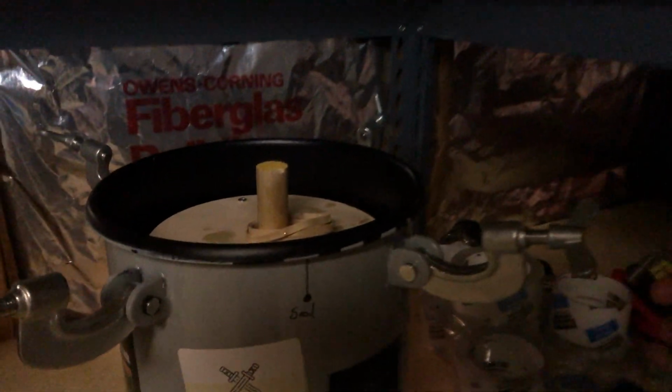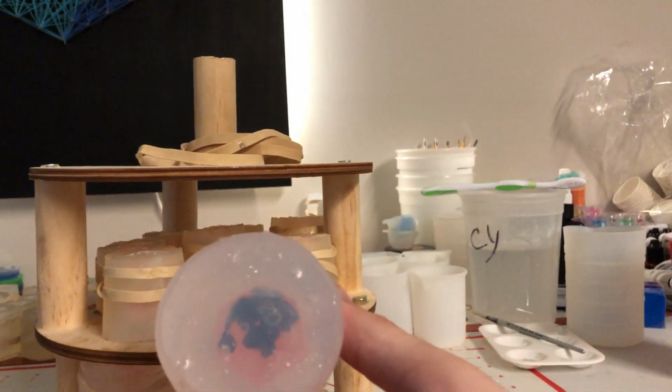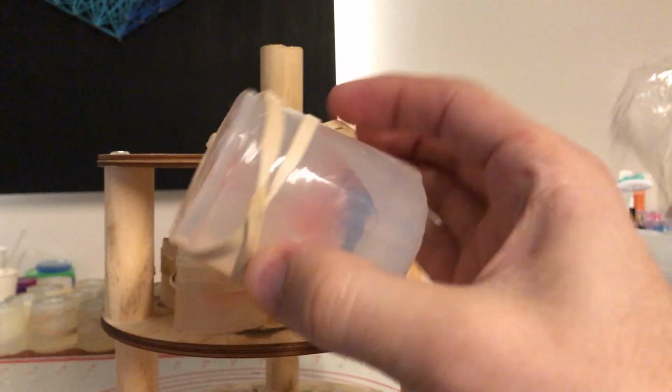Next day, it's time to pull these dice out of the pressure pot, which is now decked out with these awesome new stickers from Blue Mimic and Sweetie Fiddle. Thank you all. Grab these and run them over to my workspace that's right over in the next room. And initial looks, I'm starting to get a little bit nervous. It looks like all of the heavier mica flakes sunk to the bottom, and I wasn't as lucky with these as I am with the lighter foils.